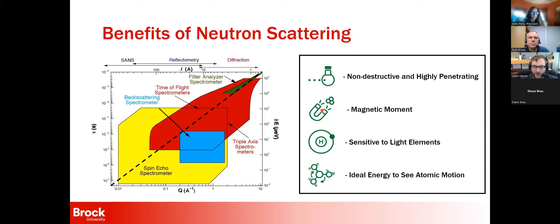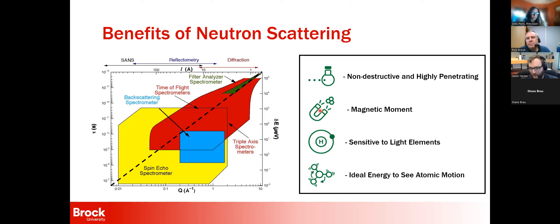Additionally, neutrons have a magnetic moment — no charge, but since they're made up of quarks with two-thirds and one-third charges, you can think of a coil of wire inside the neutron giving it a magnetic moment. We can use that to probe the magnetic properties of a material. Neutron scattering is also sensitive to light elements, which you really cannot say for X-ray scattering. Particularly, hydrogen absolutely loves to absorb neutrons — a blessing and a curse. This is why we used fluorinated glue: if we used normal glue with its high hydrogen content, you would never measure anything in the history of the universe with neutron scattering.